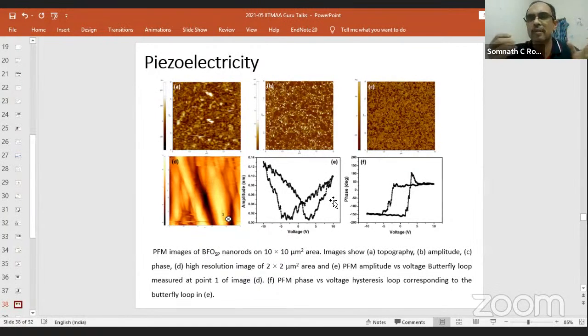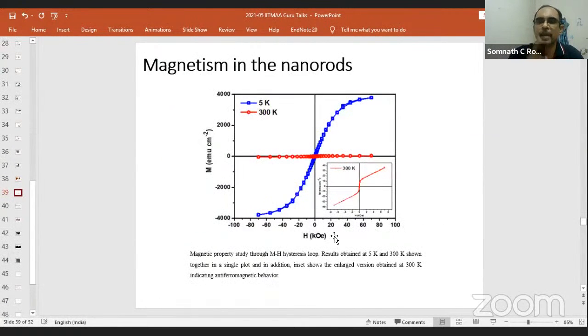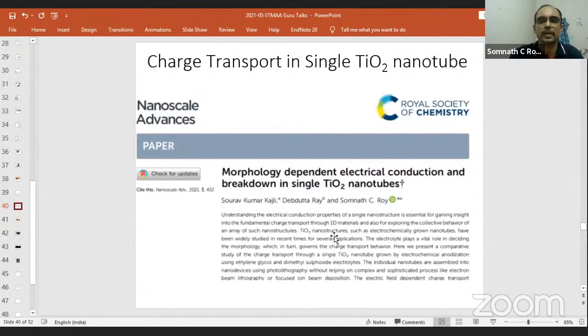When we measured the properties, we did not get very high values compared to the forms of the material that have already been reported. So we are still working on that, but I wanted to share this excitement here. As you can see, this butterfly loop is a signature of ferroelectricity. So we have shown this butterfly loop, and that ferroelectricity exists. We have also shown the magnetic properties. Yes, magnetism also exists, which confirms that we got these nanostructures of bismuth ferrite, single nanorod or nanorod arrays of bismuth ferrite, vertically grown from the glass substrate. But a lot more work is going on.